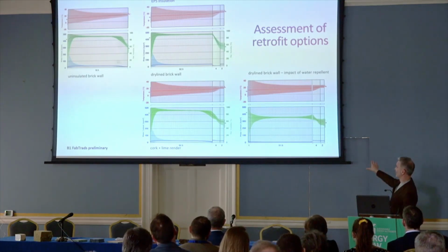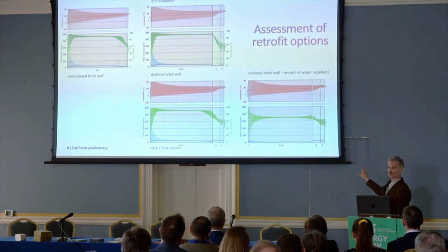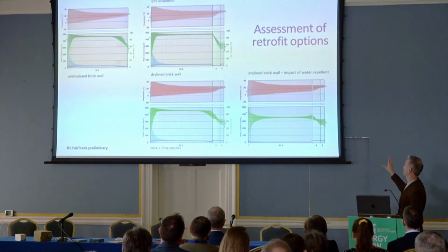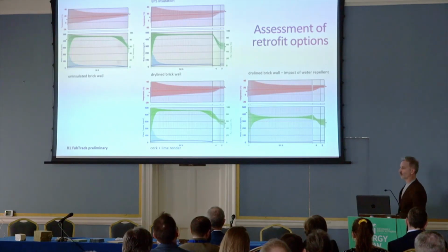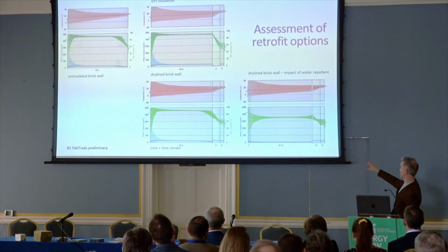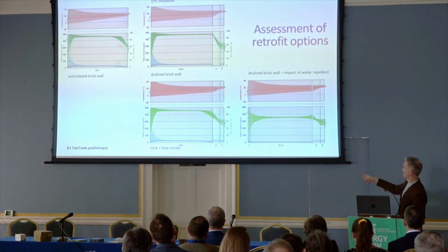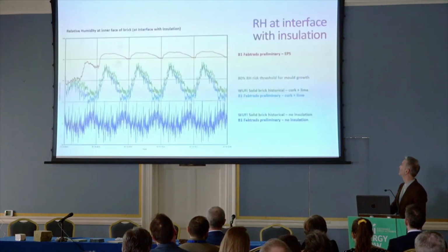And we know it's not recommended as standard in conservation practice, but we have been playing around as well with different water repellents on the surface of the brick. And the early results that we're seeing are that the moisture uptake at the surface of the brick is much lower, relative humidity in the wall section much lower, and much less risk of moisture development within it.